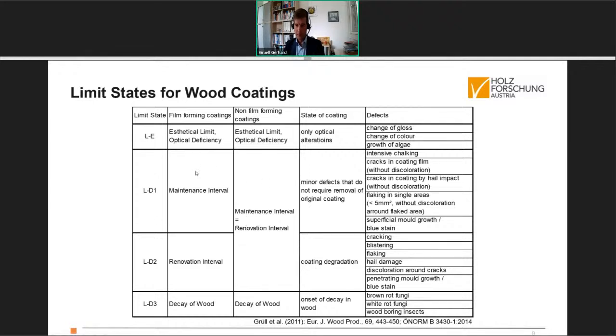Then there are other defects which determine the maintenance interval, which are minor defects that do not require the removal of the original coating. This is intensive chalking of the surface, cracks in the coating film without visible discoloration around it. That means with good adhesion. Cracks by hail impacts, for instance, flaking in small areas, and superficial mold growth or blue stain growth, so fungal growth on the surfaces, which is just on top of the surface. In this stage, you can remove some dirt and mold growth and fungal growth on the surface, and you can recoat the surface with a maintenance coat and then gain durability with this work.